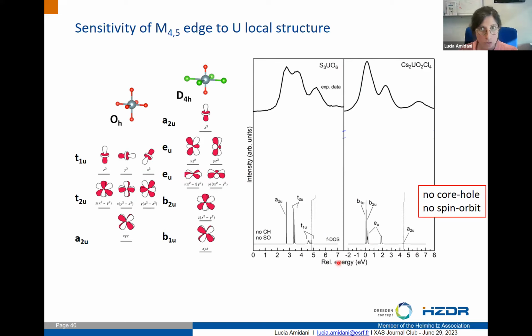And I can look at the specific orbitals, and indeed we can ascribe, in the case of the uranate, the first peak to the A2U, a single almost atomic orbital. Then we have a second group, T2U, and a third group, T1U, that gives this lower intensity. Similarly, in the case of the uranyl, we have three groups of orbitals contributing to the feature below the first main peak. And then we have the EU and A2U that are at higher energies.